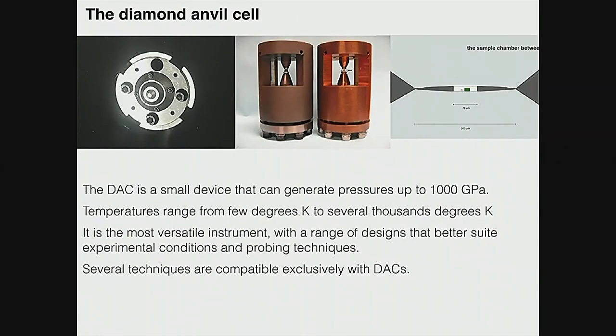So the diamond anvil cell is a device that you can hold in your hands. It allows you to push two diamonds against each other, and you put a sample in between the tips of the two diamonds. You make a sample chamber, usually using a metal foil. You make an indentation, you drill a teeny tiny hole in there, and you create your little sample chamber. This device, which is typically hardened steel, very well machined, allows you to apply this axial compression and align the diamonds, because if you don't have everything perfect, even the hardest of materials, diamond, will shatter immediately. But if you have a very good device, you can really squeeze them together.